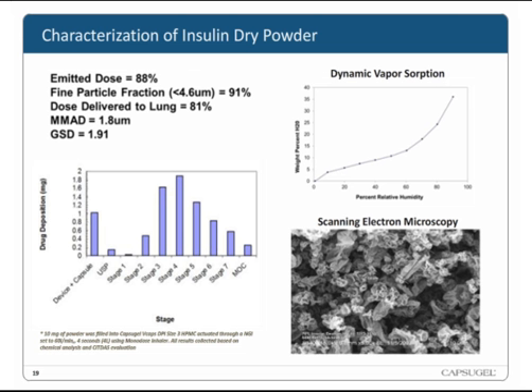And so when we tested this material, here we'll talk a little bit about some of the methodology. We looked at dry powder impaction, and the way these tests are run is about 10 milligrams of powder is put into a Capsugel VCAPS Plus special grade for inhalation, which means it's an HPMC capsule, so it excels at the lower relative humidity storage conditions that are typically required for these inhaled dry powders, meaning that we really like to store these at less than 10% relative humidity, which for gelatin-based capsules is not an acceptable condition. You get cracking and brittleness.